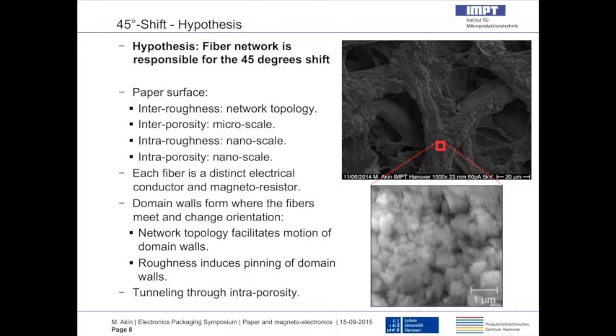So the fiber network, well, at this point in the presentation, I would like to look at the paper surface and talk to my audience about what it looks like. I would like to define the paper surface characteristics in four categories. Interroughness, which is the network topology; the interporosity, which is given by the microscale porosity, basically the empty spaces between the fibers. And if you look at each fiber, it has its own roughness, that's the nano roughness, and it also has its own pores, so that's the intraporosity.